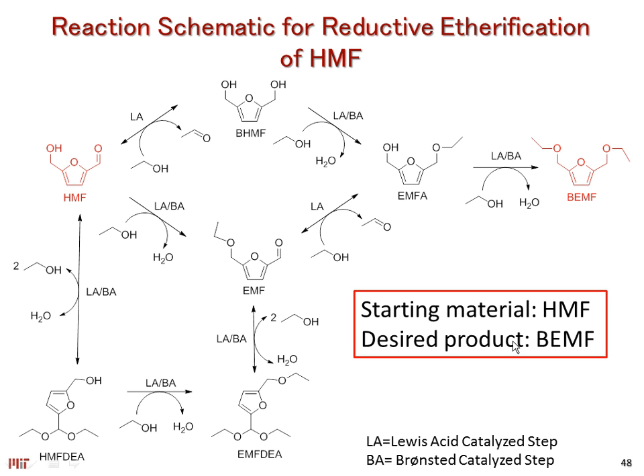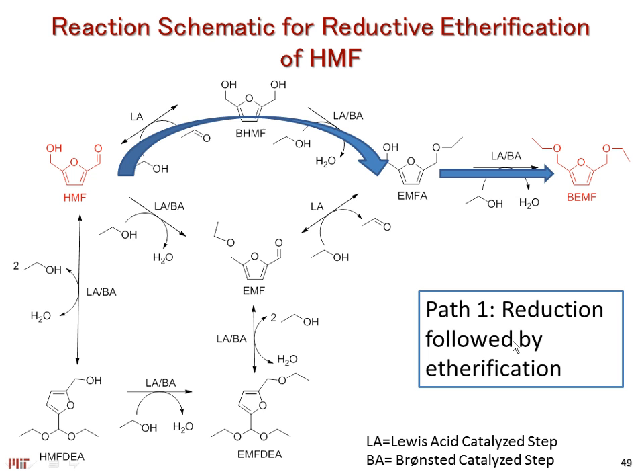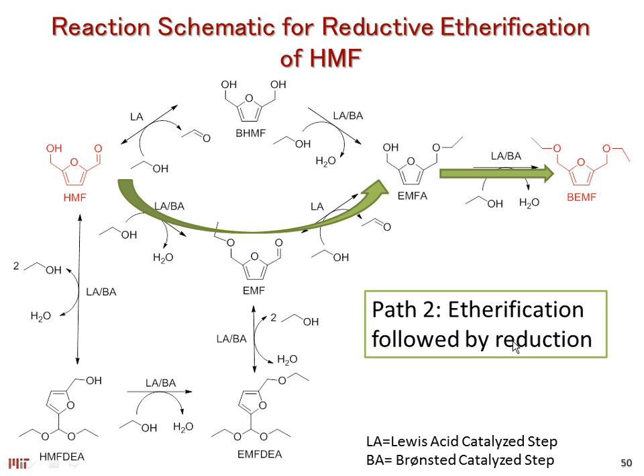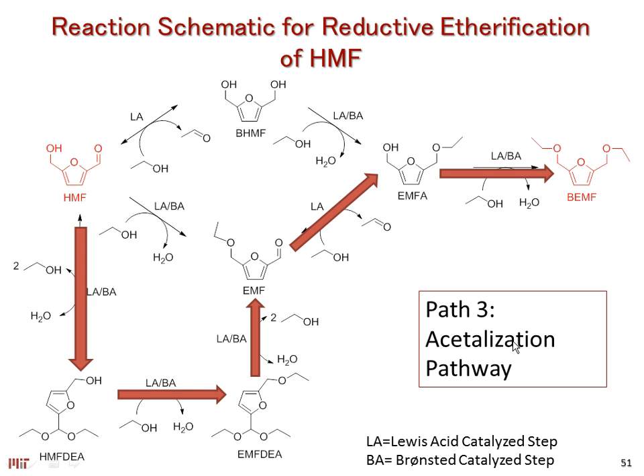Our starting material is HMF. Our target product is what we would call this BEMF, or bis-ethoxymethylfurfural. And you can see that you can go through this route over here where you do the hydrogenation and then etherification. You can have this other pathway where you do a first etherification over here on the hydroxyl group and then do a hydrogen transfer followed by etherification. Or you can go through this acetal route where you create acetals and go back and forth. It's a reversible reaction, and perhaps land here.